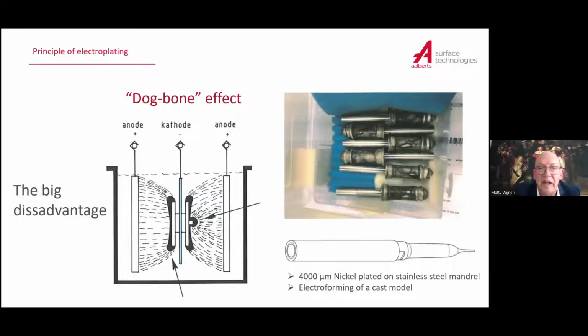Those current lines running there, the distance determines, of course, the speed of the plating. That means that where the lines are the closest to the part, the layer thickness will grow faster than in the places where the lines are longer or wider from the part. That means that in the end, you build a dog bone effect. The black, you see it, is the dog bone effect. That has to do with the fact that the current lines are not in the bath itself. That's a disadvantage which you have with electrolytic plating. You can't do anything about it. Yeah, you can minimize it by using helping methods, but in principle, it's a characteristic of the process itself.